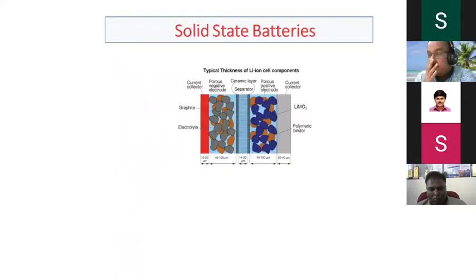Then, if you really want to use metallic lithium, we have to overcome this. We have to replace the liquid electrolyte by something else. That's why people talk a lot about solid-state batteries. The present lithium-ion battery technology uses a porous negative electrode and a porous positive electrode, with a ceramic layer separator in between, then the current collector. As I told you, graphite is the porous negative. The porous positive electrodes are lithium metal oxides: lithium cobalt oxide, lithium iron phosphate, or NMC, NCA, whatever it might be, with some polymeric binder, and completely liquid electrolyte.